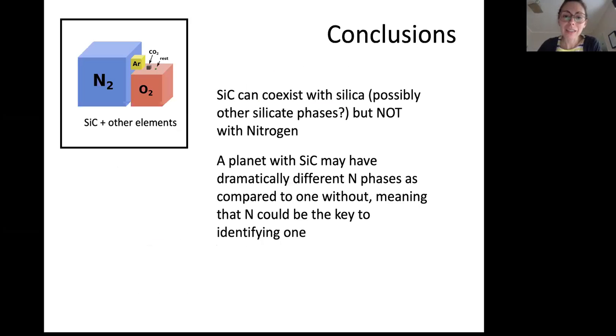So for conclusions for this part: silicon carbide can coexist with silica, possibly other silicate phases at the conditions that we studied, but not with nitrogen. And so a planet with silicon carbide might have dramatically different phases, particularly nitrogen phases, as compared to one without, meaning that nitrogen could be a key in helping to identify one of these planets.